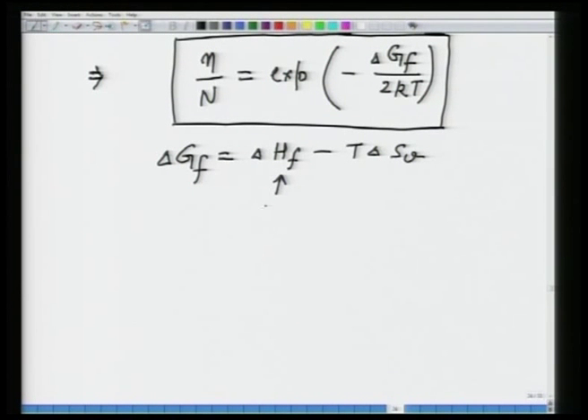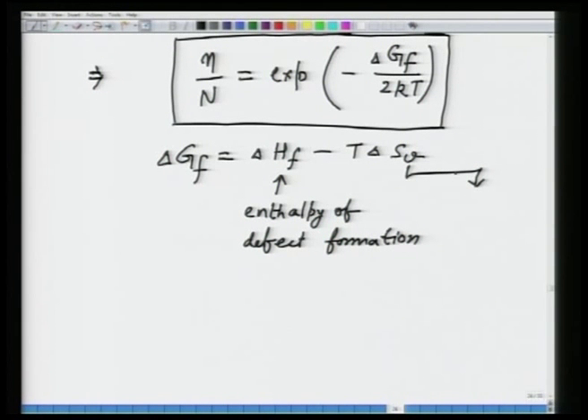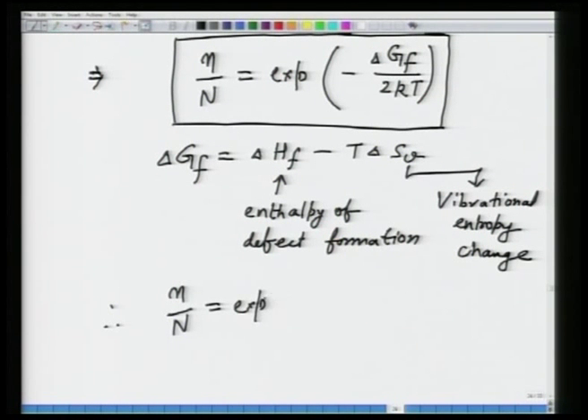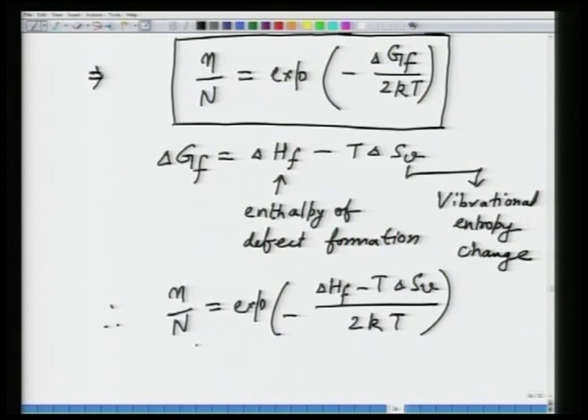v. So, this delta H f is nothing but your enthalpy of defect formation, and delta S v is nothing but, so earlier we took the configurational entropy change, this would be your vibrational entropy change. Okay. So, if you plug this in the above equation, as a result, small n by capital N will simplify to exponential of minus of delta H f minus T delta S v divided by 2 k T, and this can further be